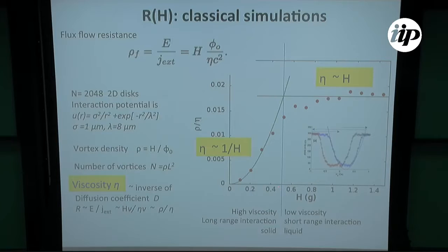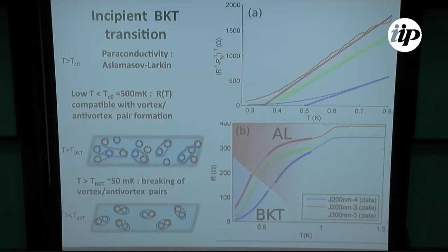Now the crucial question. Why are these vortices, these dynamics of vortices inside this system, which is on top of silicon carbide that is an insulator, and you have these contacts? To have vortices there, you have to assume that some kind of condensation energy is taking over, because the vortex requires a balance between the loss of condensation energy, of superconducting condensation energy, and the work of Meissner currents that are screening this loss.